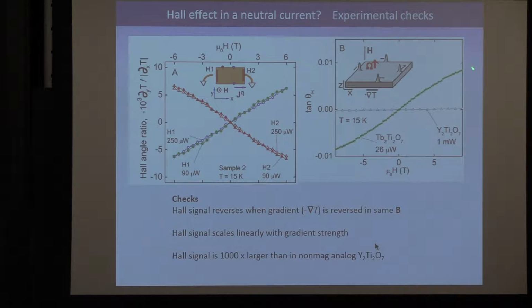You can also compare this with an analogous pyrochlore that has no magnetic moment. So this is yttrium titanate, which Kava's group was kind enough to grow for us. And you find that it has no such signal at all. And actually, it's worse than what this plot says, because here we are applying a very large power, sorry. So this is something like a factor of 40 compared to here, right? And yet there's really no signal at all.